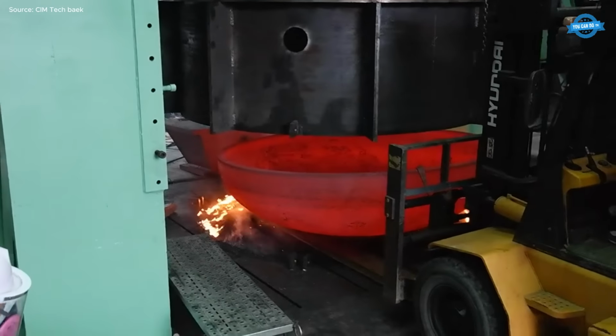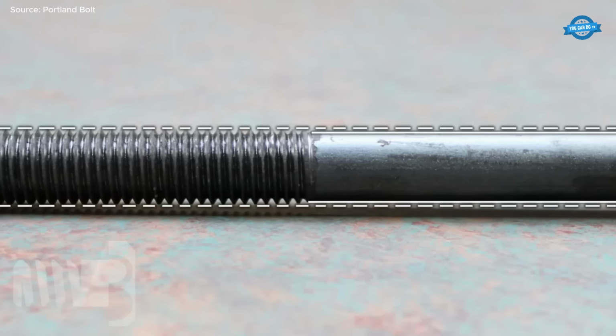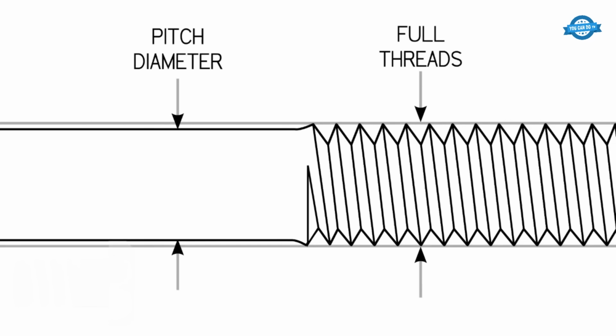Roll threading is a cold-forming extrusion process widely used in fastener manufacturing to produce high-strength, precise threads without material removal. Instead of cutting, reduced diameter round bar is forced between hardened dies that plastically displace the steel, forming the thread profile. The starting bar diameter corresponds approximately to the pitch diameter. For example, a 1-inch bolt is rolled from about 0.912-inch stock.